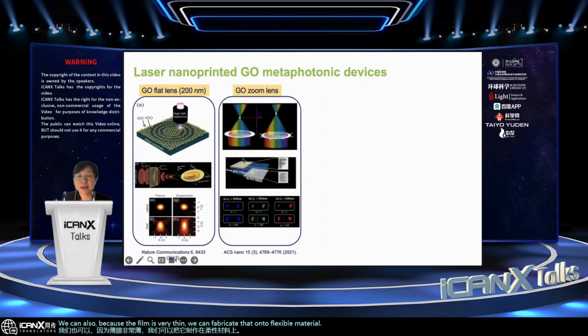In the meantime, because the film is very thin, we can fabricate it onto a flexible substrate. Normally, in order to achieve optical zoom, we need multiple lenses, like a lens kit, and the relative movement of the lenses to change the focus spot. But in this case, we can change the vertical movement into horizontal movement. And by stretching the lens, we're able to move the focal spot. So this basically achieves a flexible zoom lens, and the operation wavelength is very broad because graphene doesn't really have dispersion. It's dispersionless. So in this case, we achieved focusing or imaging across the entire visible range.